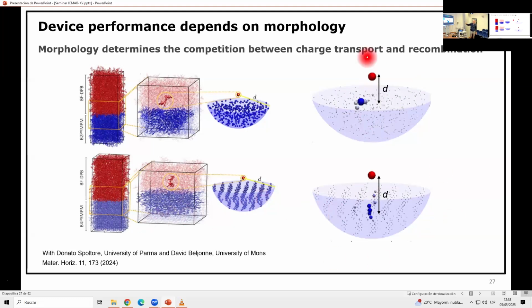And what this cartoon shows is that in the ordered case, when the charge is just transferred, on average it's further away than in the disordered case. Mainly because in the case where the molecules can order, the hole, or the electron in this case, can delocalize a bit further. So that helps, of course, for the electron to get further away from the hole. So that's one reason you want these ordered domains, not too large and not too small. So that's a bit more about what happens at the interface.